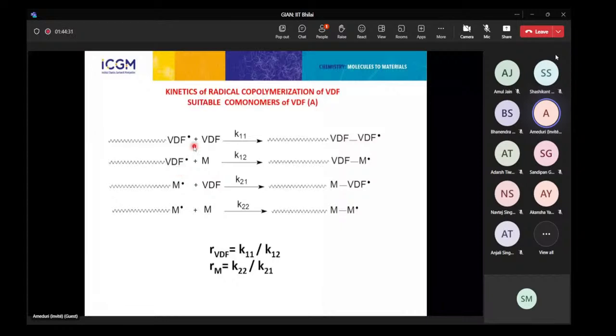So this macroradical is able to react onto M, and the ratio of K11 to K12, which has a rate of reaction, are defined as the reactivity ratio. On the other hand, if the macroradical is terminated by M, monomer, it can react either onto VDF by cross propagation or by homopropagation. And in this case, the reactivity ratio of the monomer M is K22 versus K21.